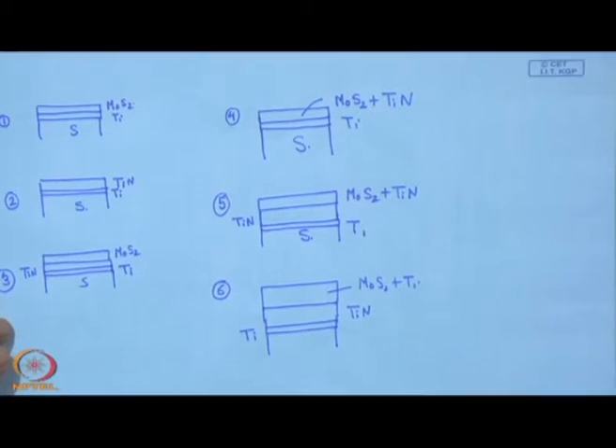So, we can examine all these 6 architectures for their performance and judge which one is the best. Following this, there can be some process variables of sputtering, and by varying those we can find out the best condition for sputtering. For a pulsed DC, keeping the frequency constant, we can change the cathode current, that means the cathode current of titanium or of MoS2, and also the substrate bias, the bias voltage for the substrate. These two process parameters can be varied and we can look into all those responses in terms of the properties of the coating.